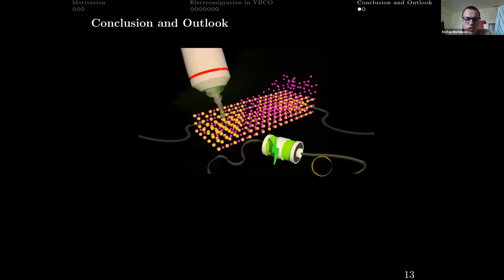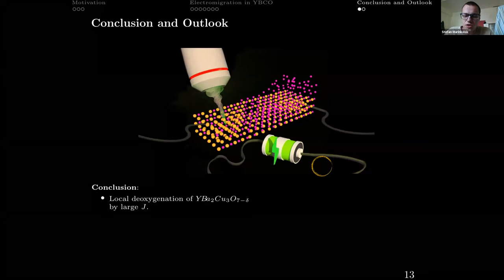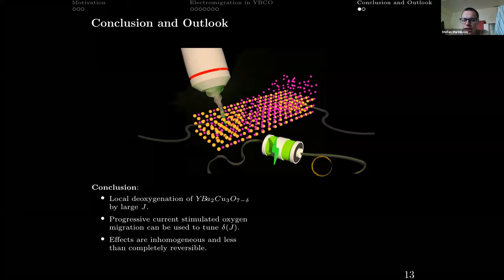So in conclusion, we have shown that local deoxygenation and change of oxygen concentration in YBCO is possible by large current densities. We have performed progressive current-stimulated oxygen migration to tune this oxygen stoichiometry. And we have shown that the effects are not completely reversible if performed by current, and that the effects are inhomogeneous and need further study. And we have shown that we agree with the findings that the electromigration is selective to the O1 oxygen.